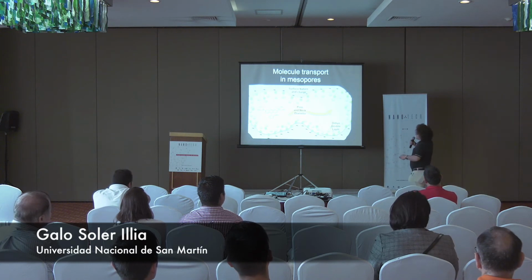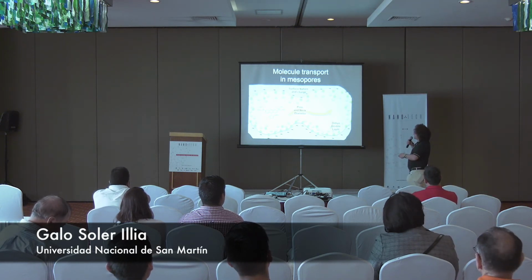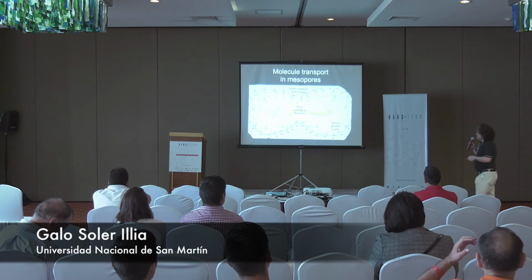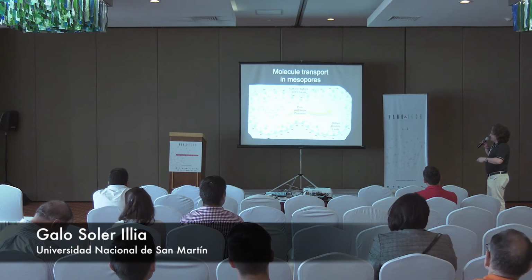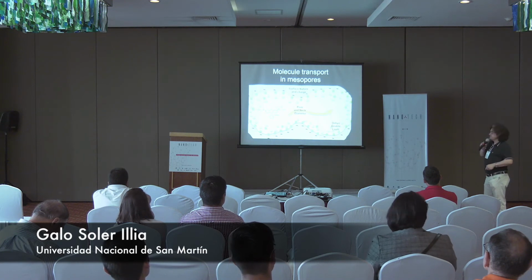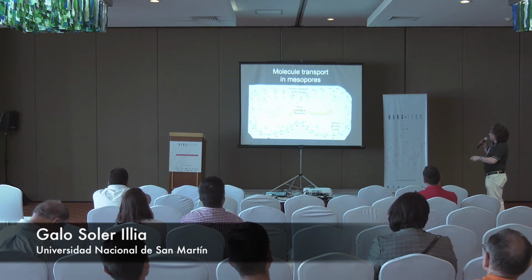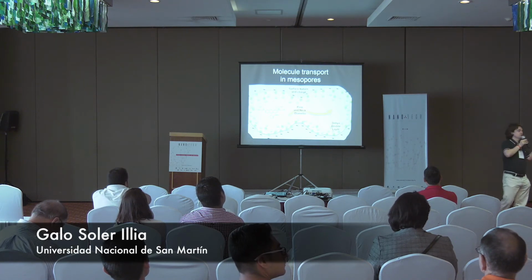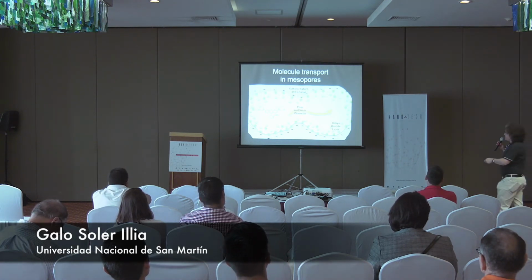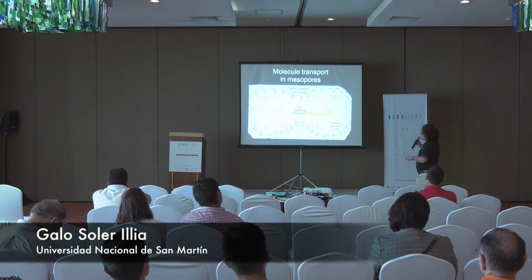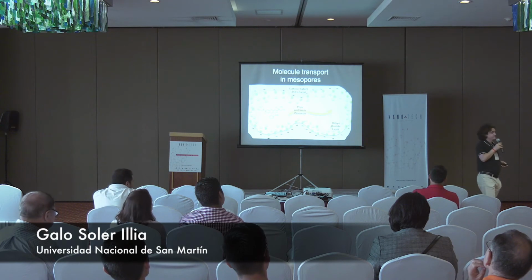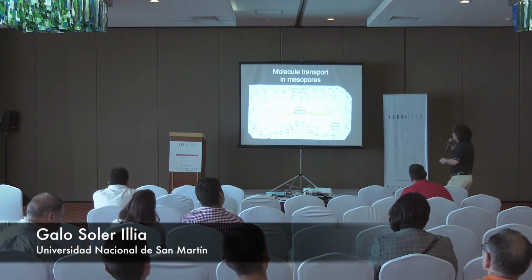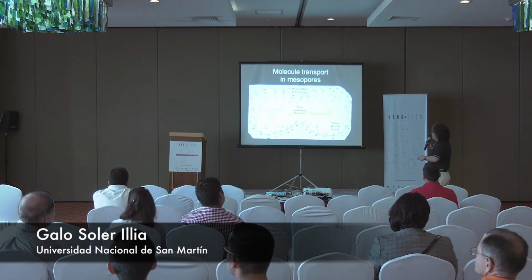What happens to a molecule that exits one pore and enters the following pore? One molecule here has to pass here, and it has a definite size. It has a solvation layer, and it also has interactions with the walls, but the walls are not just the walls. You have solutions there. And the walls might be charged. The walls might be involved in adsorption equilibrium, and also the walls can have a double layer belonging to salt solution. So the problem is quite complex. The problem of moving this molecule from here to here.